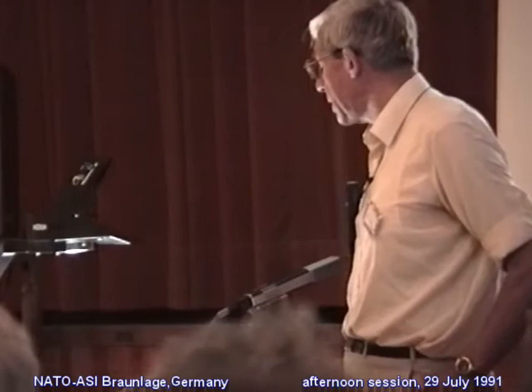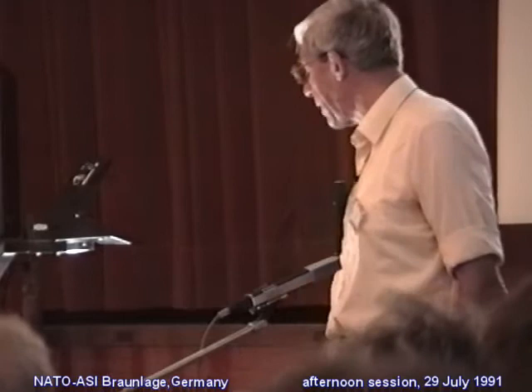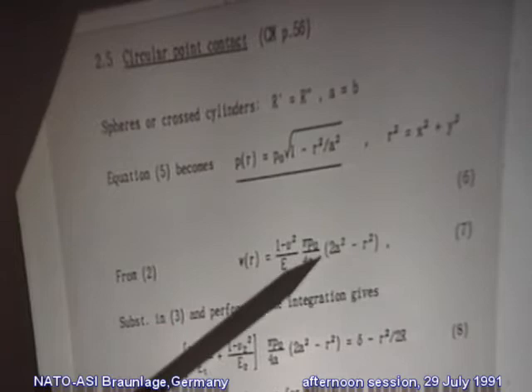If we take the case of a circular contact, an ellipse of equal axes, where the relative curvatures R prime and R double prime are equal, so that the semi-axes of the ellipse A and B are equal, then the pressure distribution becomes hemispherical, with a maximum pressure P naught and varying with radius according to that expression. The integral in that case is rather straightforward, a standard integral, and you put that into the integral equation. And again, that gives us a displacement which varies in this way with radius.